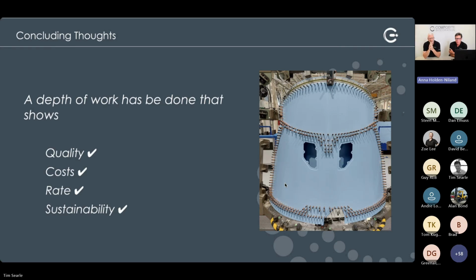High fibre fractions, low porosity levels that are challenging to measure do give us real confidence in what is possible. As far as costs go, we can't delve into specific projects, but generally speaking, we're working with raw materials that are cost effective, lower cost than pre-preg, and without the cost of storage and autoclaves. I think we'd all acknowledge that with some very thick dry laminates we can do significantly less debulking. So operationally speaking, we're familiar with laminates of perhaps in the order of 100 millimeters that can be put down in dry material without any debulks.